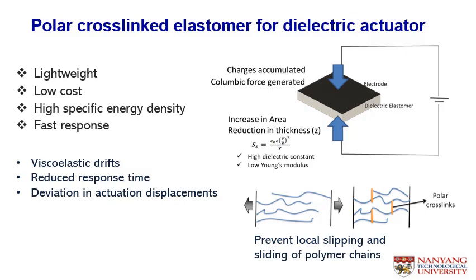The dielectric elastomer actuator has the advantages of being lightweight, low cost, high specific energy density, and fast response. However, it has the disadvantage of viscoelastic drift that leads to reduced response time and deviation in the displacement. Therefore, in order to prevent the viscoelastic drift that is coming from local slipping and sliding of the polymer chains, we have hypothesized that adding a polar crosslinker will improve or eliminate this issue.